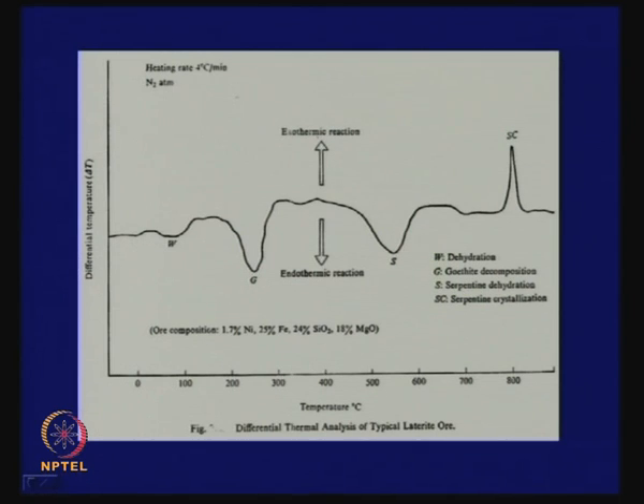Now, this is a very important observation, because it has been found mineralogically that the nickel is actually always associated with the goethite phase. So, before this temperature, nickel is inside the goethite phase, almost dormant, but the moment that goethite decomposition takes place, nickel that was associated with goethite is now liberated. It becomes active, nickel oxide becomes active and it can be very easily reduced. Then we come to the third endothermic peak.